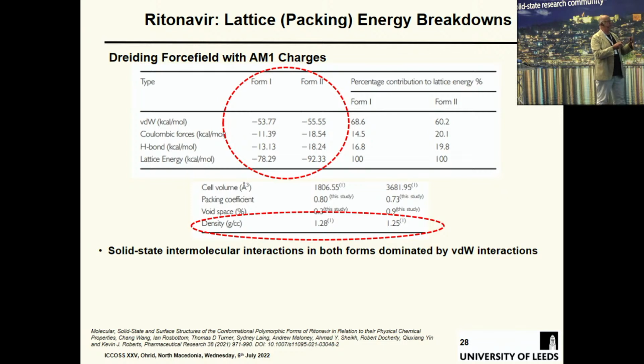Then we can have a look at it. With some degree of geekiness, we can just keep on going, and we can start to look at how those forces break down. And we can see the important thing here, as I mentioned earlier on, how important van der Waals interactions are. For both of those structures, they contribute the bulk of the lattice energy contribution. And it's higher in Form 1 because it's more close packed than Form 2.